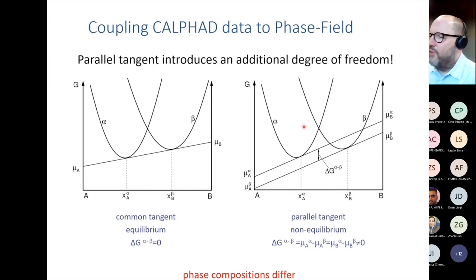And the solution to that was to move away from the common tangent, but introduce parallel tangents. So we got one tangent to the alpha phase, one to the beta phase. Both have exactly the same slope. So we have the difference in chemical potentials, mu B in alpha and beta, and mu A in alpha and beta, is the same for both. That's a parallel tangent. And that introduces the extra degree of freedom and allows us to get the driving force in order to advance the phase field solution.